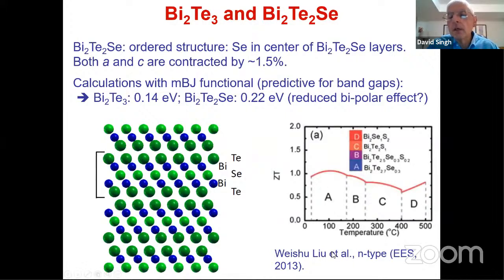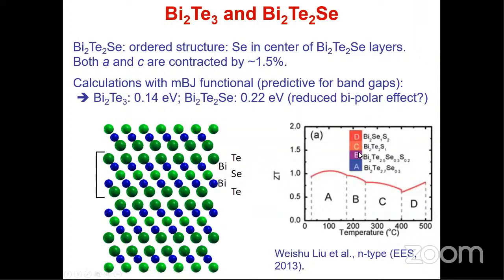This is from an experimental group. They made different alloys with sulfur and selenium and showed that, this is in degrees Celsius, the previous chart was in Kelvin, the ZT could be high, around 1, for these different alloys at higher temperature where bismuth telluride is not good. But they never achieved this magical material where the ZT just went up. We thought maybe the band structure is quite complicated and similar to lead telluride, and it could be a matter of properly optimizing the doping level.